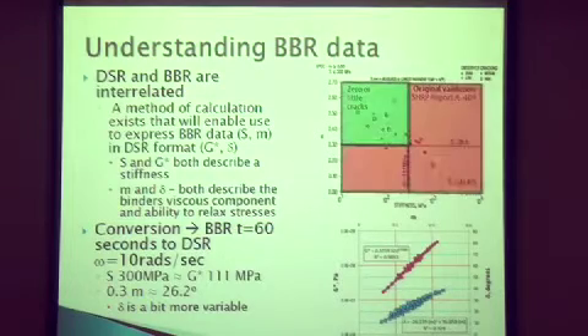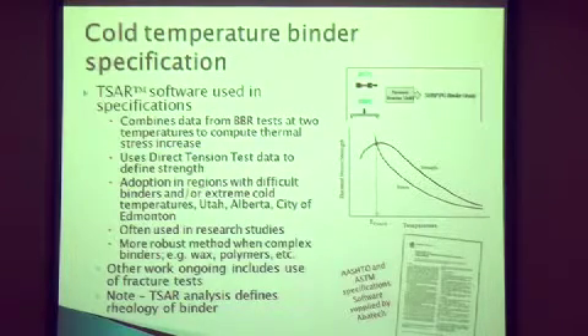And if I want to put that, I can put that as this was the no cracking, this was where they have cracking. You see, I also have G star on here, and I also put phase angle on that graph as well. So we can relate those two devices very well. So if I want to, I can obtain the dynamic properties at the high stiffness region from the bending beam rheometer, and I can combine that data with my analysis of dynamic shear rheometer data. It's a very powerful rheometer in getting information.